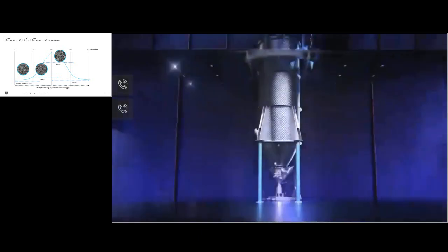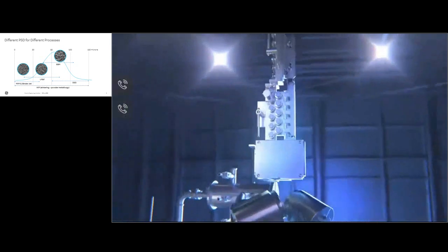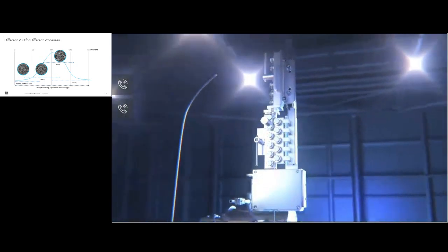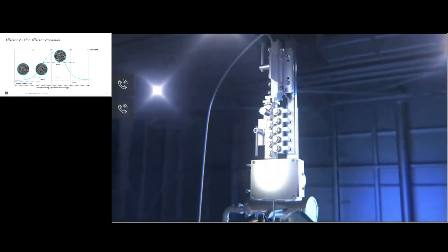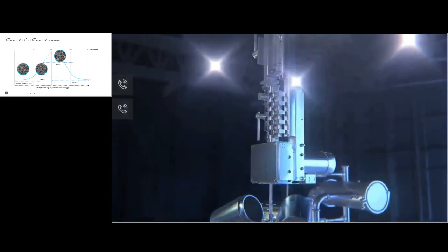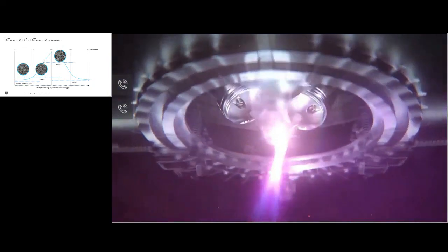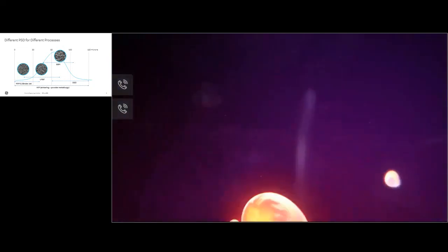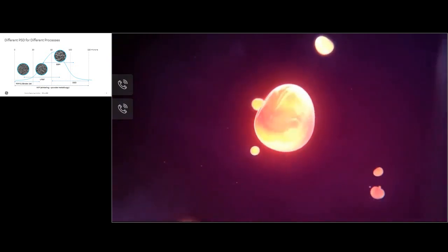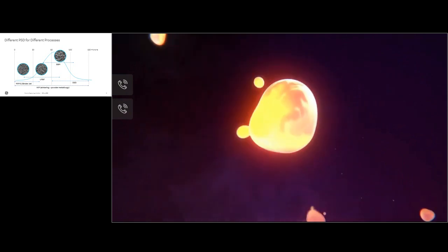The atomization process begins with a solid wire being fed from a spool into the atomization unit. Using a wire instead of a metal stream allows for greater control over the feed process, granting improved stability and accuracy during this stage. In a single step, high-temperature plasma torches melt and atomize a small section of the wire. The two-story tall atomizer is large enough to provide the necessary residence time for the particles to form and settle in the most optimal manner.